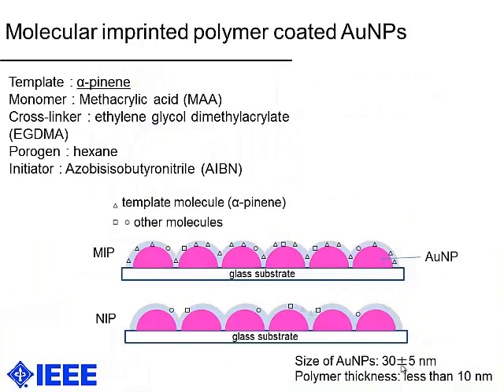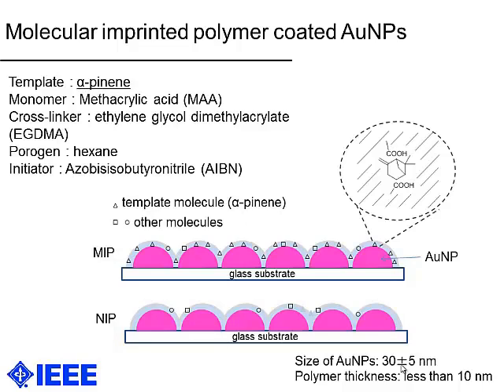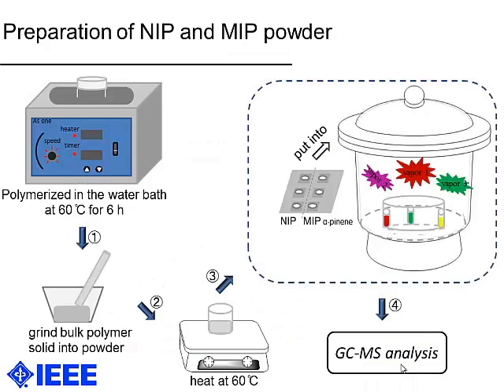And in this research, the molecular imprinted polymer-coated AuNPs sensors are shown like this one. Template here, we use alpha-pinene, monomer, cross-linker, and imprinted polymer initiator are shown like this one. And theoretically, these alpha-pinene vapors will be entrapped in the thin molecular layer on AuNPs. First, in order to verify whether there is some MIP effect in the powder, we made the experiment shown like this one. First, polymerize in the water bath at 60 centigrade for 6 hours and grind the bulk polymer solid into powder, and then heat it at 60 centigrade to evaporate all the target vapors, and then input it into this kind of equipment for the absorption experiment.